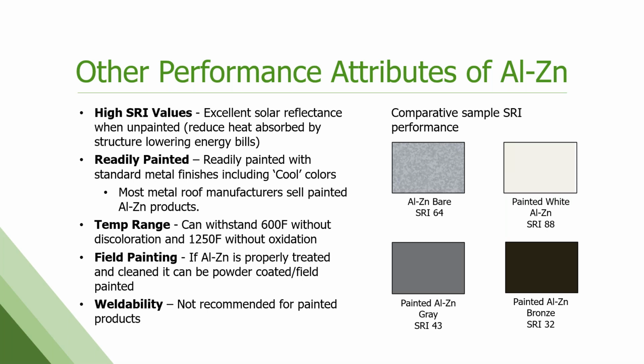That's a requirement. Can withstand a wide temperature range, 600 Fahrenheit continuously without any kind of discoloration, up to 1250 without any severe oxidation over time. In its bare form, it is readily paintable in the field if someone wants to paint it after installation. It can also be powder coated, if that's desired. It can be welded in its bare form as well. We don't recommend that for the paint because it burns the paint, but it can be welded.